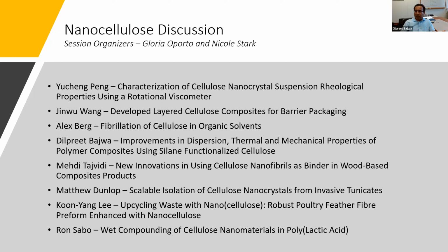And then overall, from this study, which is still continuing, we found that the 1% silane treatment for 1% CNC was the most effective. It helped to improve the thermal properties, mechanical properties, as well as the dispersion of CNCs compared to 5% or 2.5% treatment. We also found that an increase in the silane concentration above 1% led to a decrease in storage modulus, an increase in tan delta, and thermal degradation.